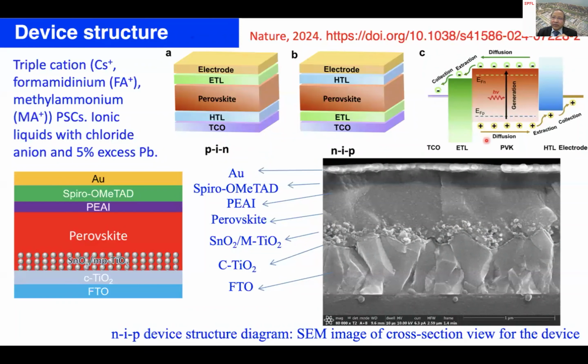Now coming back to the mechanism, you have a perovskite, you create positive and negative charges, and then the positive charges diffuse because you aligned the hole transport in such a way that the positive charges are extracted into the hole transport material and go to the contact. Similarly, the electrons in the conduction band of the perovskite are injected into the electron transport layer, and then you have a charge separation.